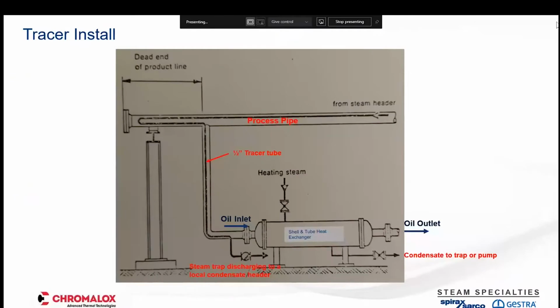In terms of dead end of product line, it's very, very easy during the installation to actually forget about the dead end, and it's very important, because what more often than not happens is that tracer line there will then be taken straight the way down here, and we forget about this dead end condition. The oil is still flowing here, and of course we've got a stanchion here that will actually absorb a lot of the heat, so we've got to offset that. So that tracer tube will be 1/2 inch, as this example shows, 1/2 inch tracer tube, and it's drained via a steam trap. So it's critical we get that oil flowing into that shell and tube heat exchanger, and we put on a steam trap there that's discharging condensate as soon as it forms.